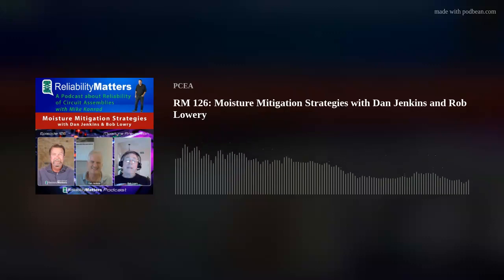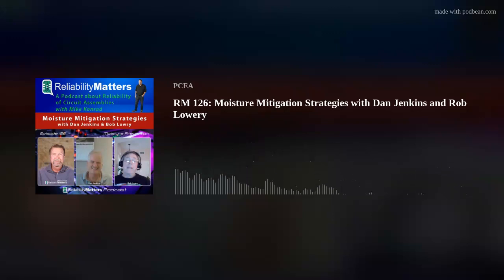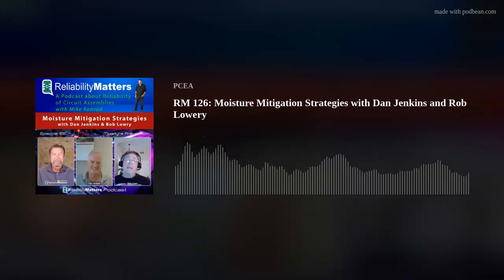There's a specification in the military system — MIL-STD-883, test method 5011 — that tells you how to qualify coatings for how well they coat, how conformal they are, how moisture resistant they are, and how dry they are inherently within themselves. What's sad is that not many people in the industry ever implement that document to qualify the materials they're going to use, which leads to exactly the kind of problems we've talked about.